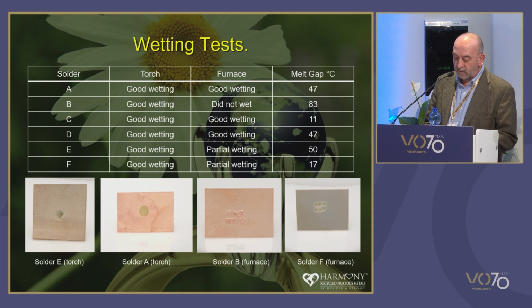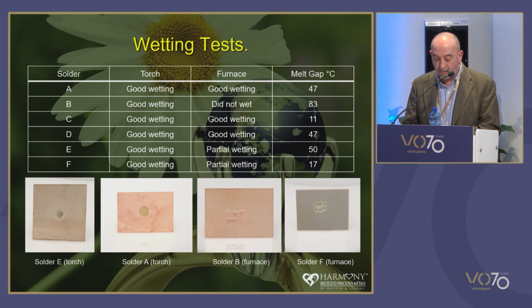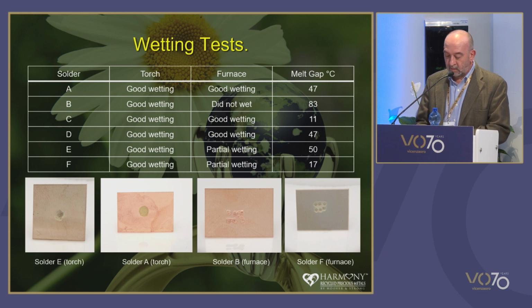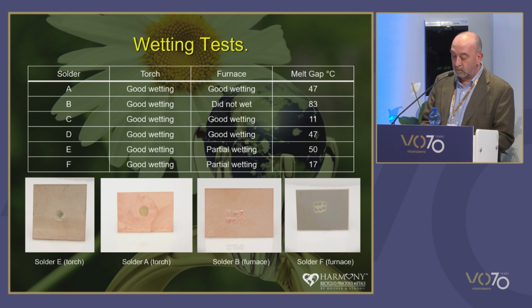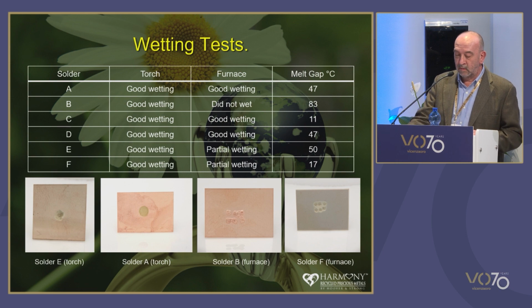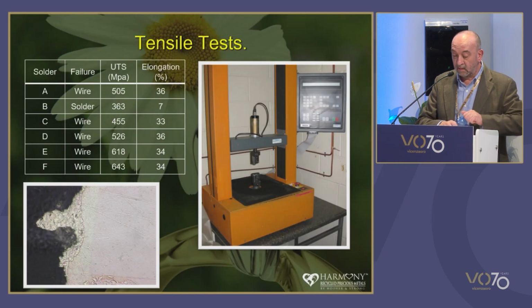Also note that the worst result was solder B, and it came with the solder with the largest melt gap. So from these results, we can possibly say that the solders chosen are more sensitive to furnace conditions than direct torch. So after that, we decided to do some tensile tests.